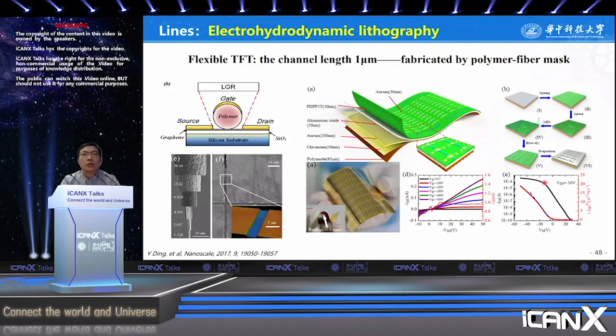Now let's show how to use the method to fabricate a flexible TFT. Just 3 steps are needed in patterning the electrode. The mask is printed directly, followed by sputter coating of a thin film. Then, removing the mask, one can get the patterned film. The resolution reached as small as 1 micrometer, so that a small channel length is generated for TFT. This method can replace the mask layer. More important, it can work on curved surface. A flexible TFT array can be fabricated and that shows significant transistor performance.